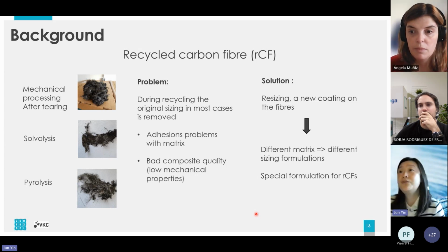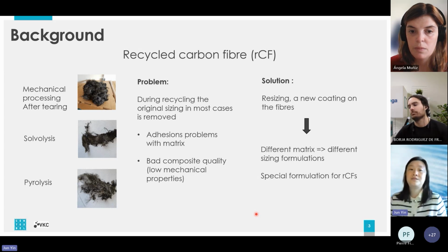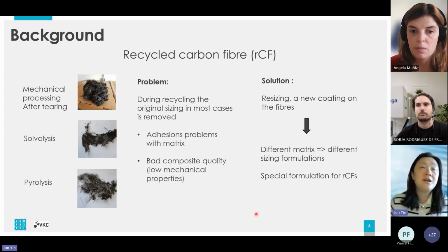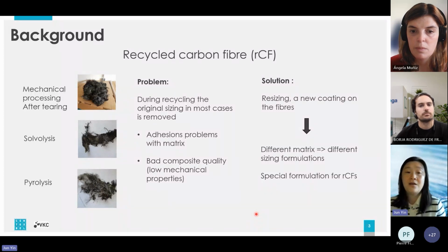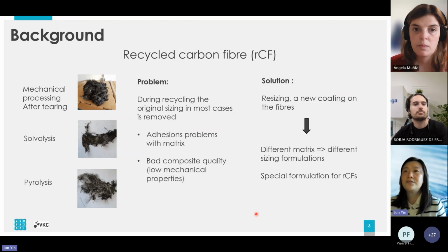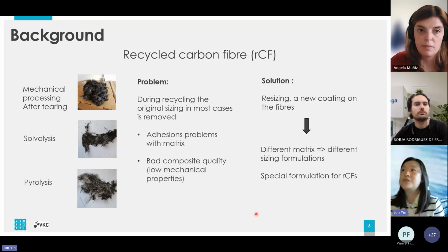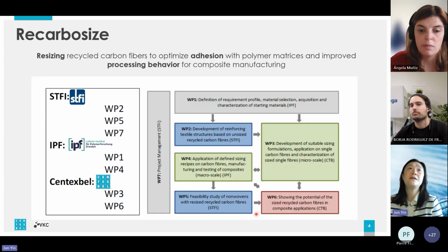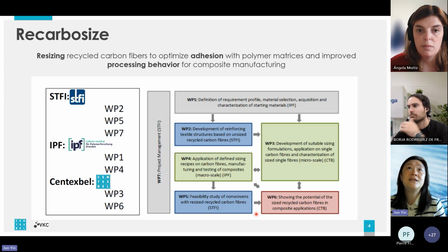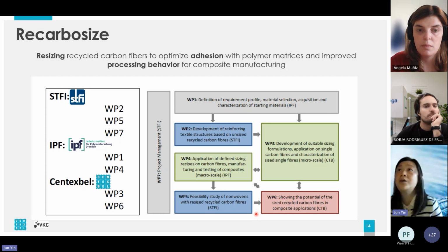That means if we want to reuse this recycled carbon fiber in different matrices, we should develop different sizing formulations. And also we need a special formulation for recycled carbon fibers. Normally, different recycling companies of carbon fibers have different formulations, but they normally keep them separate for each company. So we don't know the formulation very well. So we want to develop it in this project. Recarbosize: it's resizing recycled carbon fiber to optimize adhesion with the polymer matrix and improve processing behaviors.